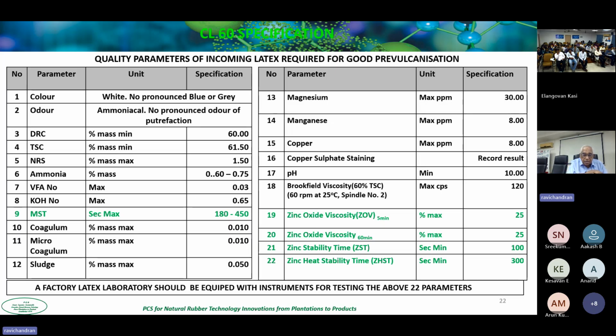The MST gives us the mechanical, physical stability of the latex. And what you see on the right-hand side, zinc oxide viscosity, zinc stability time, zinc heat stability, that's the chemical stability of the latex. So you have the physical, mechanical stability on one side and the chemical stability. We want the latex to come in at these parameters so that we know there will be no coagulation and no batches will get spoiled.